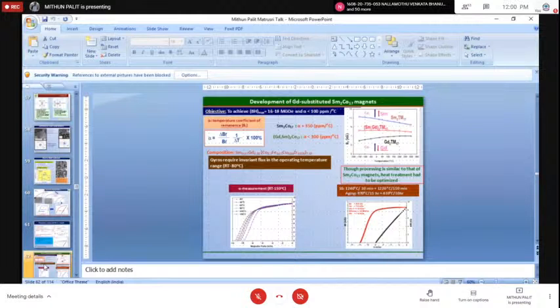In fact, we can compute a parameter called alpha, which shows the temperature coefficient of remanence, meaning how remanence is changing with temperature, and we have achieved a temperature coefficient as low as something like 60 to 80 ppm.